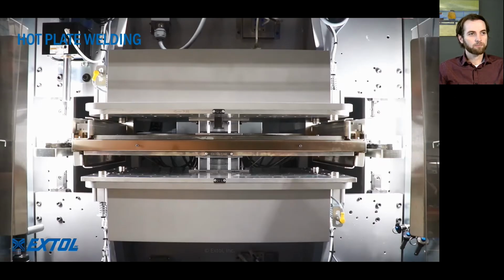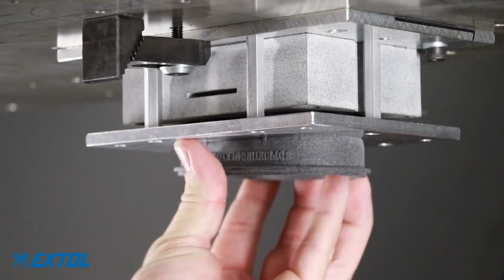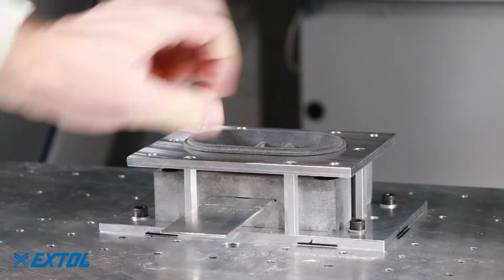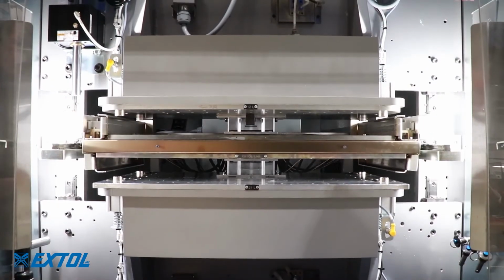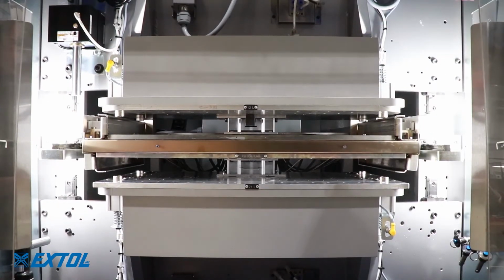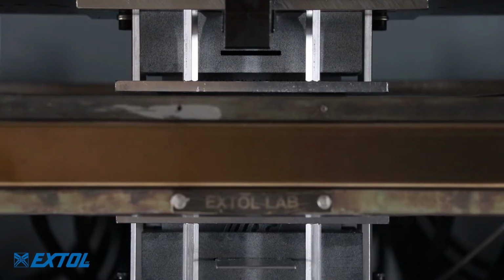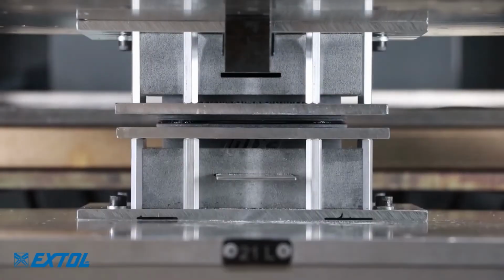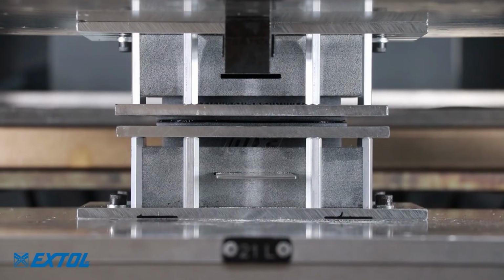So here's an example of the hot plate welding process in action. So the 3D printed parts are loaded into a fixture. The horizontal heat plate is about 500 degrees Fahrenheit, and the weld ribs on the part touch that heat plate to melt. The heat plate is then retracted. You can see the black melted weld ribs, and then the parts are held together under force until the material resolidifies.